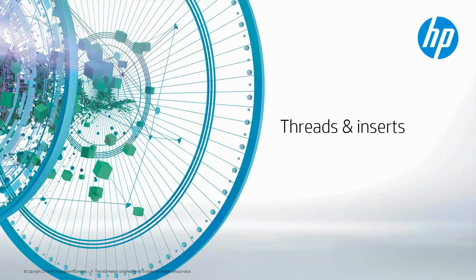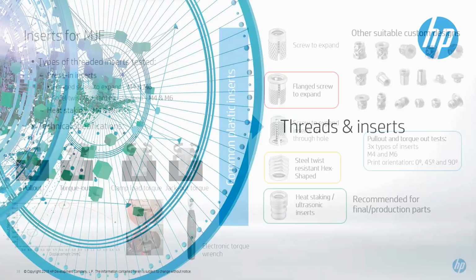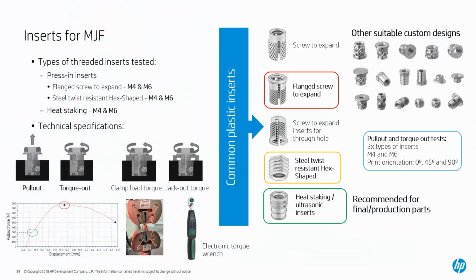And then to our last section, we're going to briefly go over threads and inserts, mainly inserts. MJF readily accepts different types of inserts. If you don't need to print a thread, and printed threads are okay in certain circumstances, but inserts are going to be a much better option depending on the connection that you need and the force that you need to use it with. We went through a lot of different types of testing, and the three that you see circled, the red, the yellow, and the green, are the three that we focused mostly on. The best ones that we have found are the heat staking, and then we would move up to the steel twist, and then the flange screw expanding type.